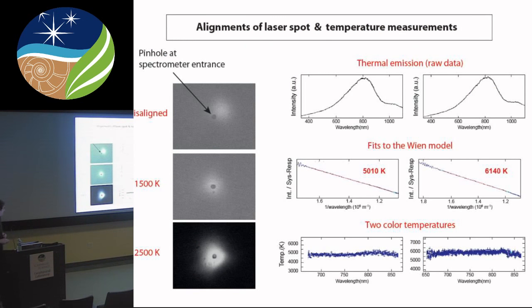This is the kind of temperature measurement we obtain. This is the entrance of the spectrometer. The laser spot here is similar to this one, similar temperature, but this is misaligned, but this is classical. Everyone who has done laser heating experiments knows that this is not so difficult to do. This is well aligned, and this is well aligned too.